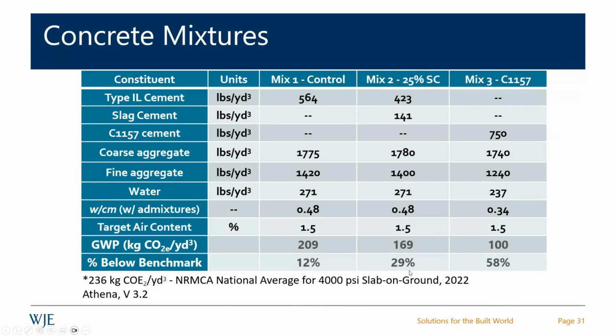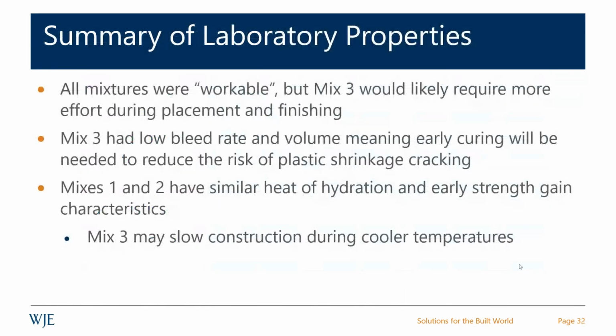But when we went to an 1157, that was basically 10% clinker at max, but an alkali activated slag, we saw these dramatic reductions. Basically, we did rigorous laboratory work again. All of the mixes were considered workable, but we found that placement and finishing of mix 3 was going to be difficult. And it also had very, very low bleed rates and volumes and also very low heat. So there were some concerns about mix 3.